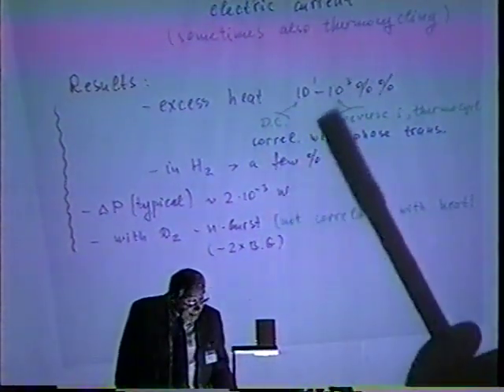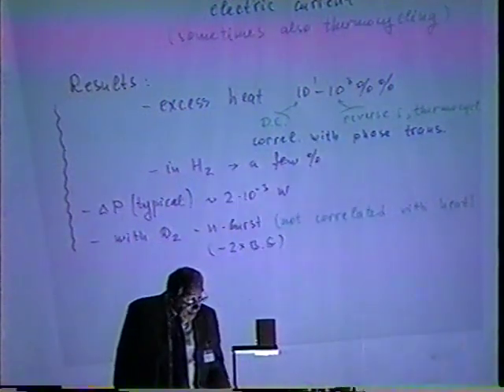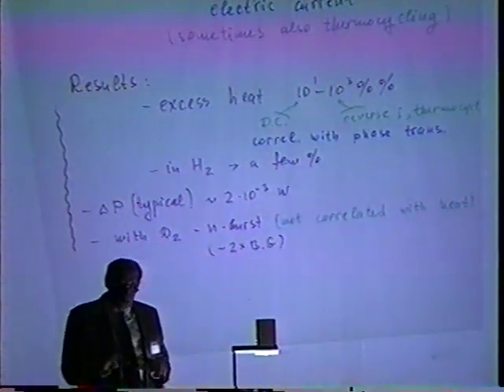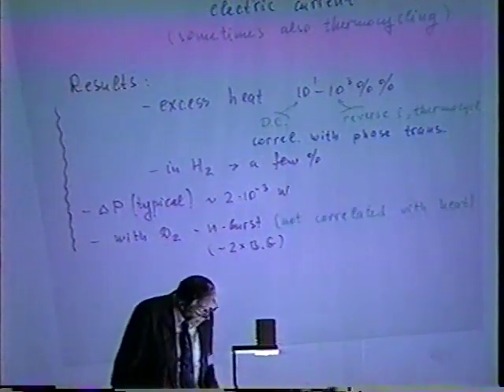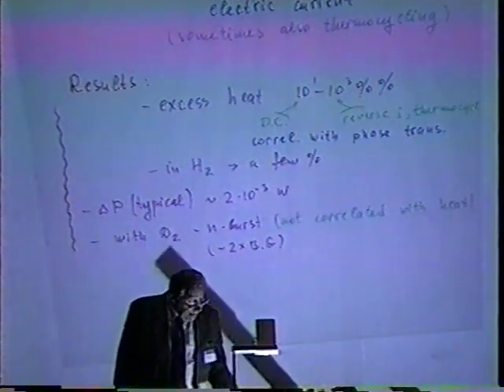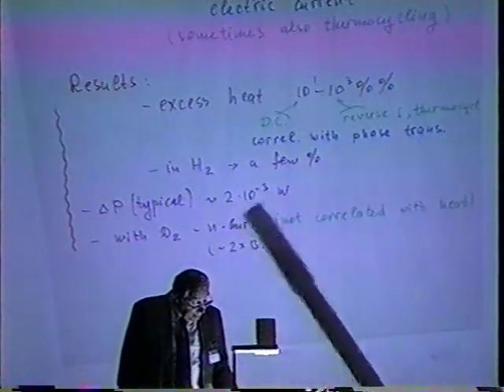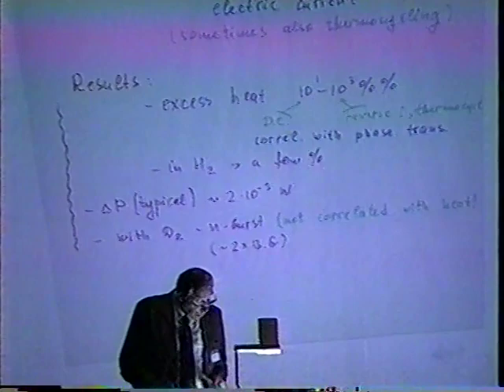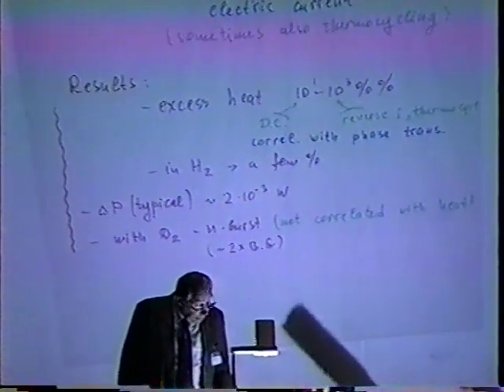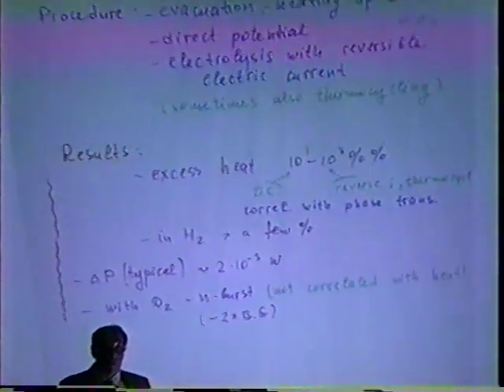Now, when they used hydrogen instead of deuterium, the effect was rather low, only a few percent. The typical value of increase of power was about 2 by 10 to the minus 3 watt, so it's a very low level. And they also observed a neutron boost. However, it was not correlated with excess heat.